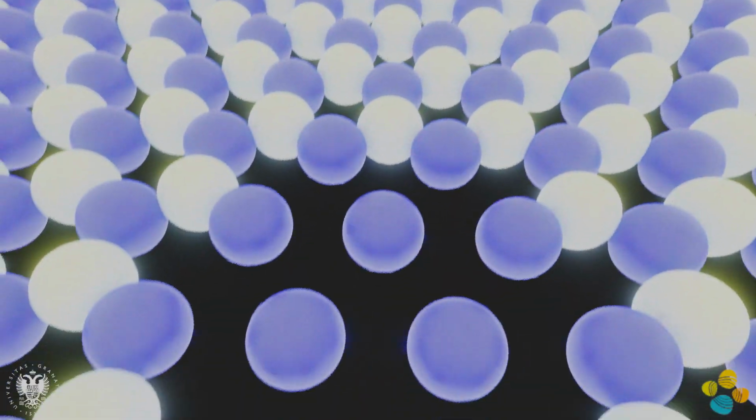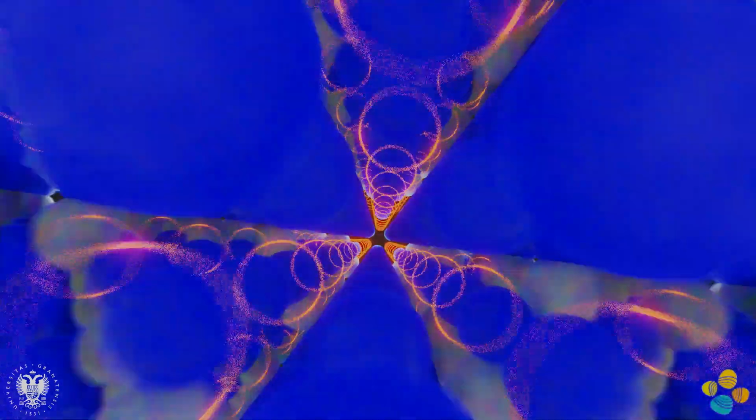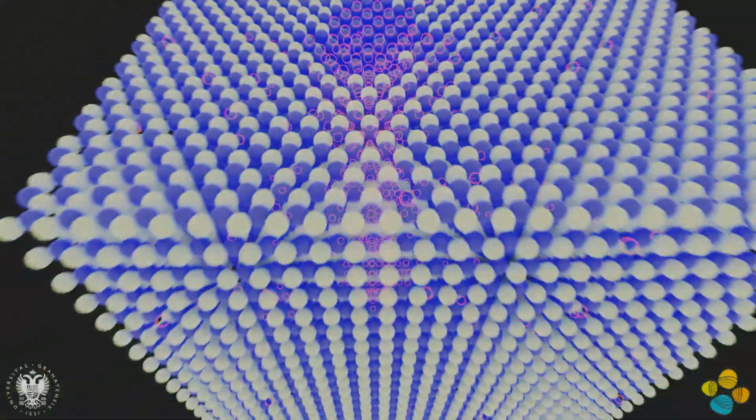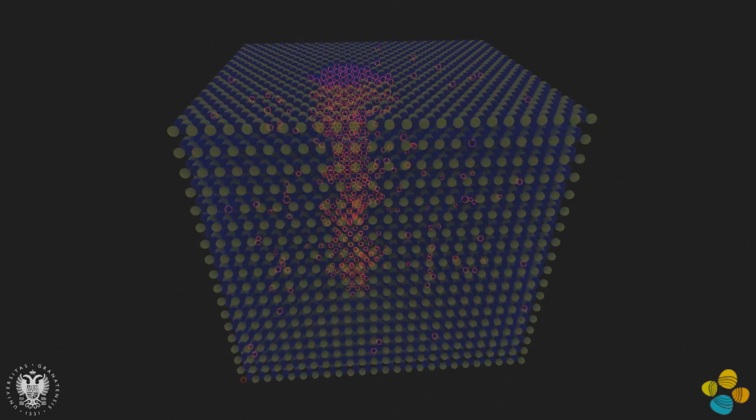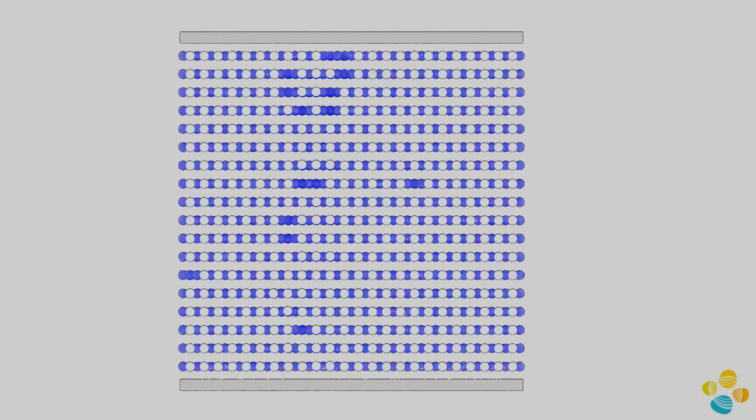It is known that regions of high density of defects favor memristor resistive switching operation. Conductive nanofilament formation is linked to defect-rich regions where a high concentration of boron vacancies is found and where metallic ions can diffuse.